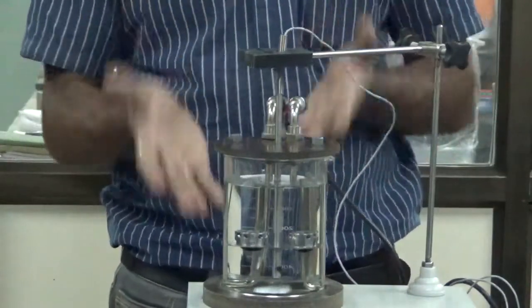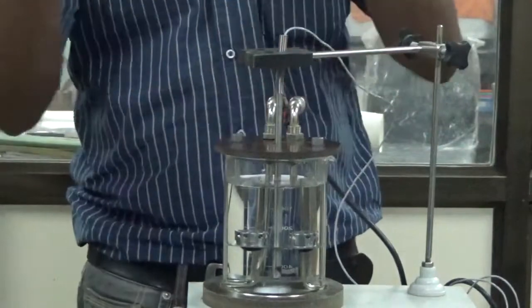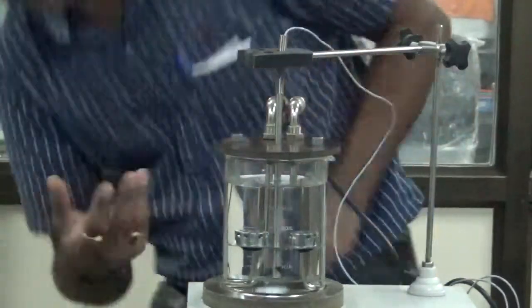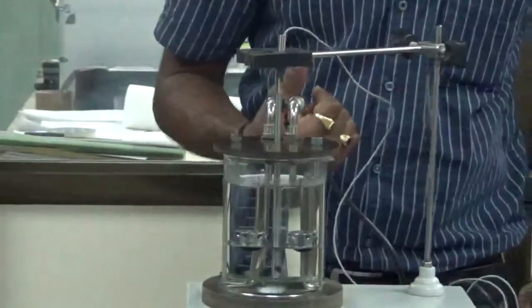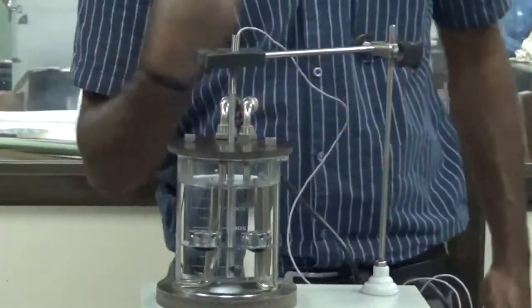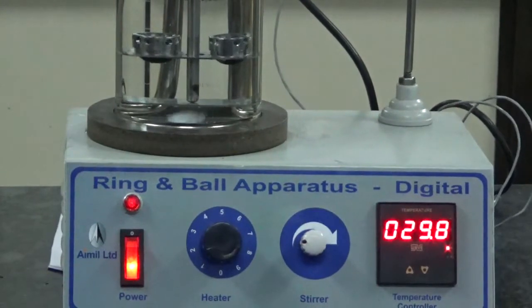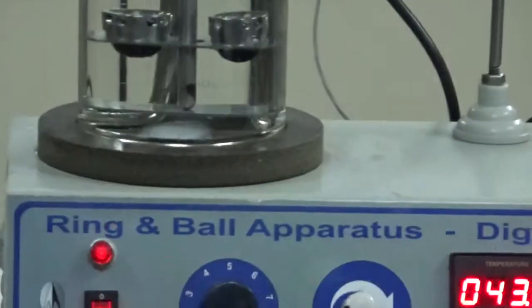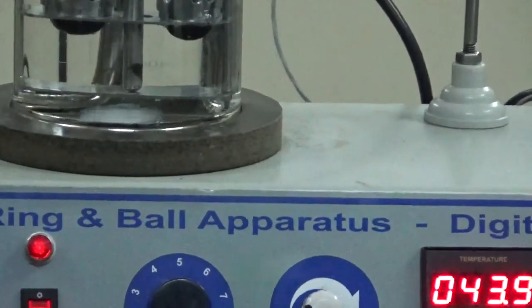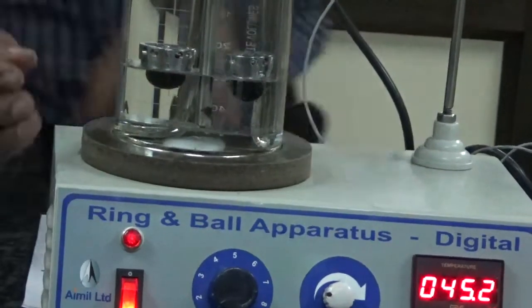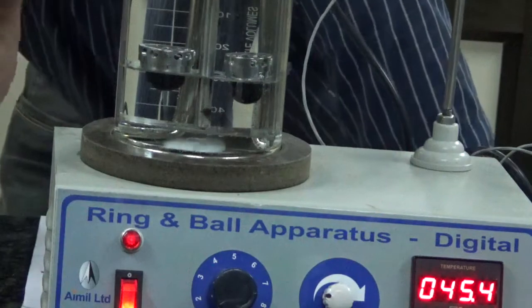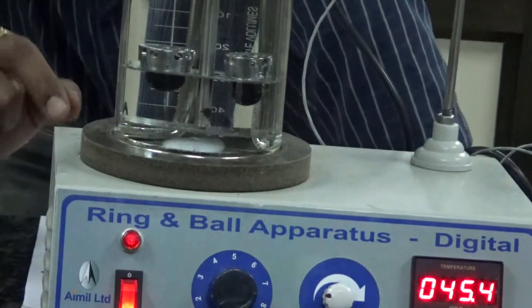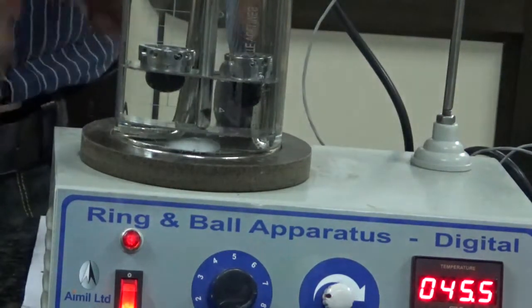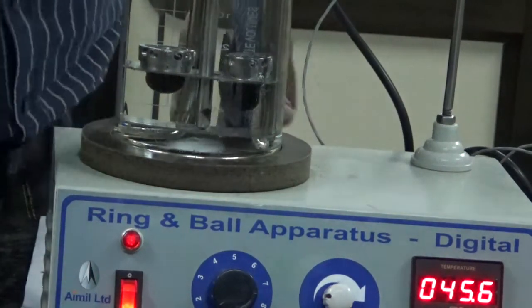Now we need to wait until the temperature reaches the softening point. Once it is near the softening point, my bitumen is going to start flowing. Now my material has attained some softening, so you can see the steel balls are bringing my bitumen sample downward. The moment it touches, the temperature at which it touches will be our softening point.